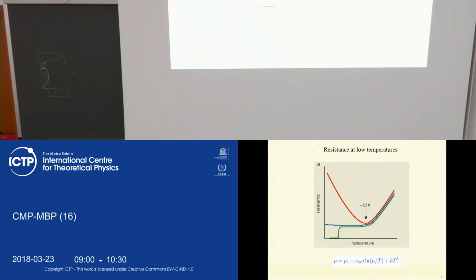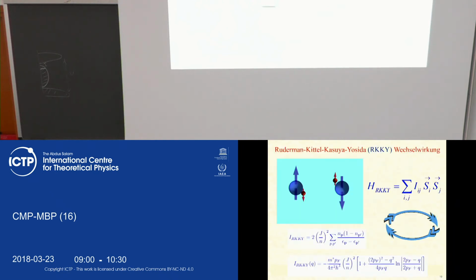So you see that one of the ingredients is the Kondo effect, which actually leads to an increase of the inverse transport time because of increasing backscattering, so to say. What actually happens physically is that the interaction of electrons with localized spins increases the backscattering very much, which leads to an increase of the resistivity. There is yet another effect if we take into account the interaction between two spins. As I said, from the very beginning we assumed that the lattice is very much diluted. However, the same electrons which interact with local spins and contribute to the Kondo effect can also mediate the interaction between two spins. This interaction is known as the Ruderman-Kittel-Kasuya-Yosida